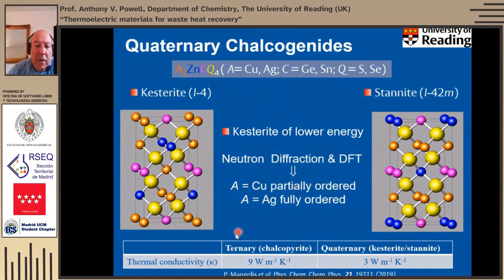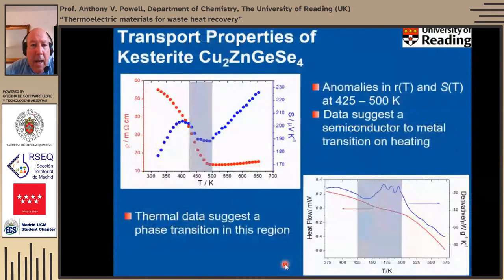And the main reason for our interest in these, as I said, the chalcopyrite itself has got a thermal conductivity of about 9 watts per meter per Kelvin. That of the kesterite stannite type materials is about 1/3 of that at 3 watts per meter per Kelvin. Now, the kesterite end member itself has a slightly odd property, which I'll come back to, hopefully, if I've got time towards the end, in terms of a phonon-liquid electron crystal.